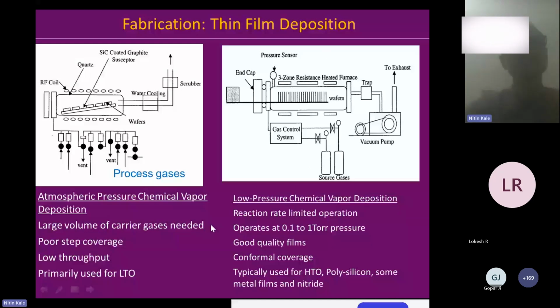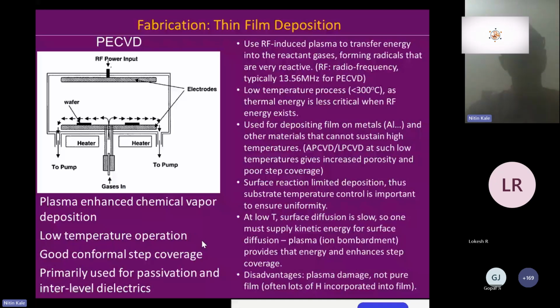You have also what is called as plasma enhanced CVD. So what is this? So typically CVD processes, chemical vapor deposition processes, happen at high temperatures. The temperature could be something like 600 degrees Celsius. But if your substrate is not silicon, instead it is, let's say, a plastic, a polymer, then you will need to do these depositions at lower temperatures because plastic polymers typically cannot withstand high temperatures. So what do you do?